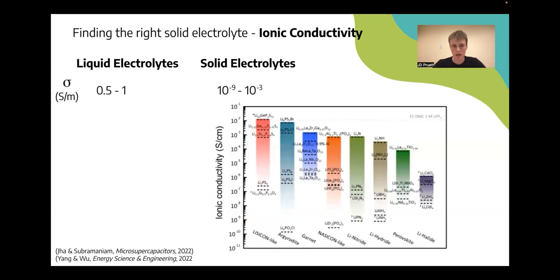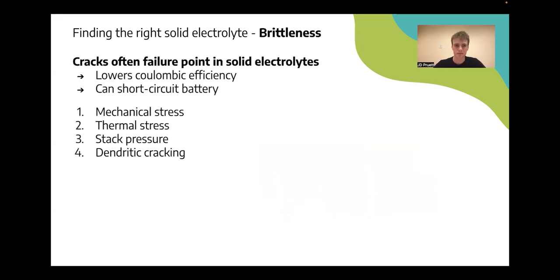So when we look at measures of conductivity in liquid versus solid electrolytes, measured in Siemens per meter, you can see that a liquid electrolyte usually hovers around 1/2 to 1, while solid electrolyte is orders of magnitude lower than that. Even the highest ones we've achieved in a research context, looking at 10 to the -2, 10 to the -3 Siemens per meter. So this is the first and most difficult challenge that we would need to overcome.